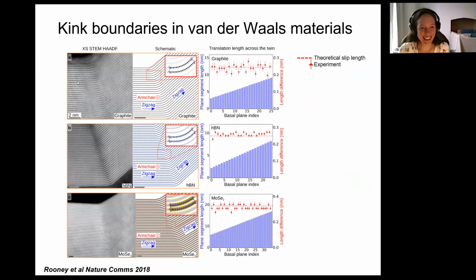We have some ripples here, for instance, on the left. Not on the bending one, but just on the left here. I was just wondering if this is real. This bit here? Yes, we see some ripples. I think it's probably scan distortion. I'm not sure without going back and checking, but I would expect it's probably a small amount of scan distortion that you can see there. We do see some strange effects, like this difference in contrast, because we aren't in a perfect high angle annular dark field imaging mode. It's probably more like annular dark field, and so we see a small amount of diffraction contrast, which effectively shows the strain that is present within that bend. So we often see those sort of features. You also sometimes get effects of a little bit of curtaining, which is due to the FIB milling of the material.